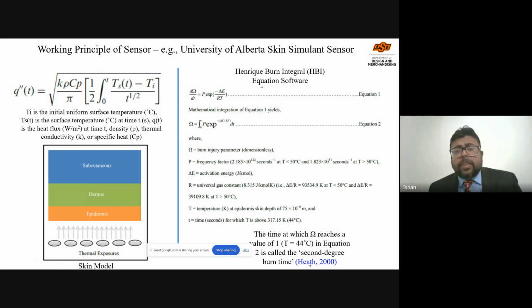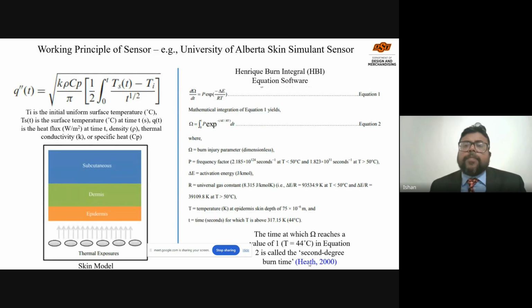Remember that the first degree burn could occur, especially in India or somewhere, if the temperature is very high during the hot summer, when people come in from outside, they could see that their skin is red. It could be a little bit of first degree burn, not so dangerous. People could take a good bath or something. But second degree burn is the first stage of burn where it is very dangerous to the human skin. That's why most of the time we try to measure the second degree burn time, because after that the third degree burn is very bad and fourth degree burn is worst, because it damages the human tissue, bones, everything. So this is the Henriques burn integral software.